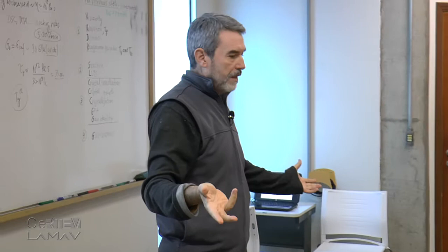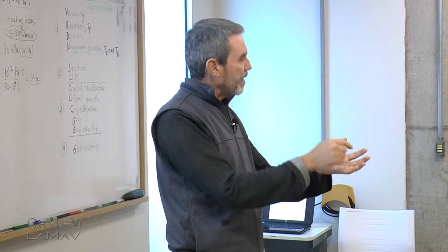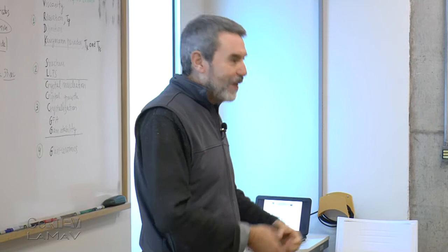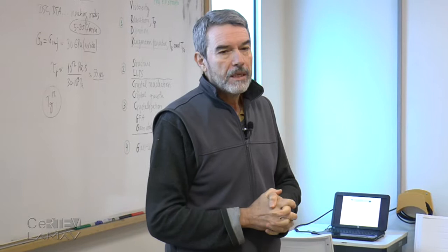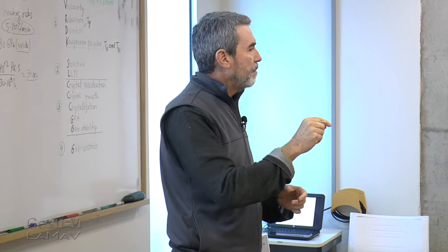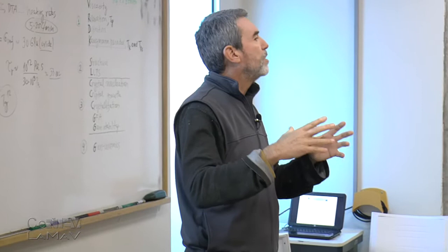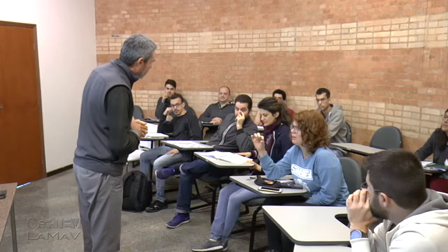A sphere will have internal stresses. If you have a large sphere, the surface will be cooled down much faster than the interior parts. And this is a problem you cannot solve. You cannot fast cool the interior of a glass. There's no way to get the heat out, especially because glasses have low thermal conductivity. Glasses have a very short phonon mean free path because they're disorganized. So all oxide glasses have very low thermal conductivity, which means a large gradient in temperature. The surface is always cooled much faster than the interior. What if you have a very thin plate of glass?